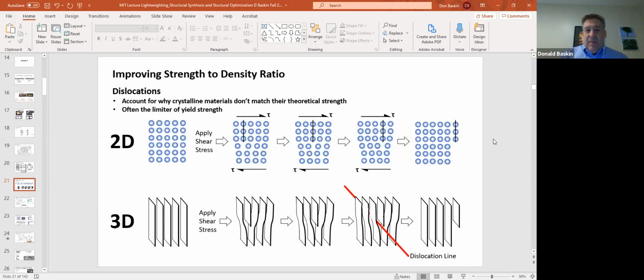Okay, so metals, as you know, are made up of regular crystalline arrays of atoms. When a material goes from a liquid to a solid, somehow magically through thermodynamics, the atoms line up in rows and columns, and they form crystals. This happens over and over again. Each grain is like a perfect crystal. Sometimes when these crystalline lattices form, you get a missing column of atoms. That missing column of atoms leads to a distortion in the lattice, and that missing column is called a dislocation.